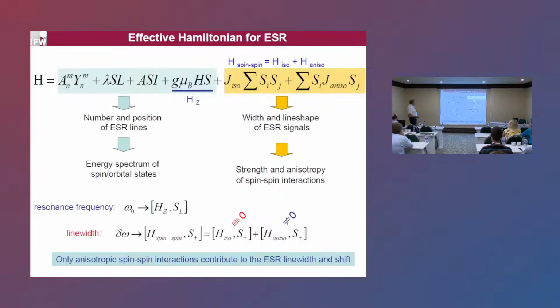And now that brings me to electron spin resonance, because it turns out that exactly this method is very sensitive to this kind of anisotropies. If one considers the general effective Hamiltonian used in ESR spectroscopy, one can see that the ESR response is sensitive to many kinds of interactions: the crystal field, spin-orbit coupling, interaction of electron spins with nuclear spins, the Zeeman coupling, and on the right-hand side, the Heisenberg exchange and the anisotropic exchange. Very importantly, the ESR response is in particular very sensitive to the anisotropies, because anisotropies give rise to a finite width of the ESR signal and to a shift of the resonance position of the ESR signals in a spin system.